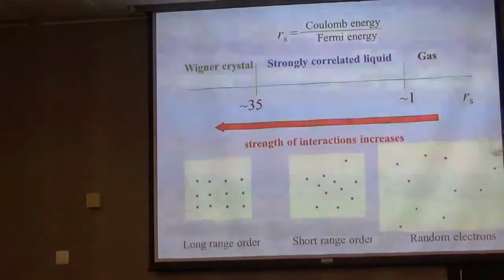So if this ratio R sub s is less than 1, we have an electron gas. They don't feel each other, they're just randomly running around. Now, suppose we have extremely strong interactions between electrons, so strong that the ratio is bigger than 35. Because the numerical calculations show us that if the ratio is bigger than 35, electrons form a so-called Wigner crystal.